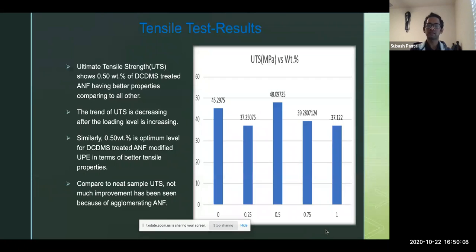Tensile test results. Ultimate tensile strength shows that 0.50 weight percentage of dichlorodimethyl silane treated aluminum nanofiber has better properties compared to others. The trend of ultimate tensile strength starts decreasing as the loading level is increasing. Similarly, 0.50 weight percent is the optimum level for dichlorodimethyl silane treated aluminum nanofiber modified polyester in terms of better tensile properties. From the chart, we can see at 0.50 weight percentage, the ultimate tensile strength is 48.09 megapascal.